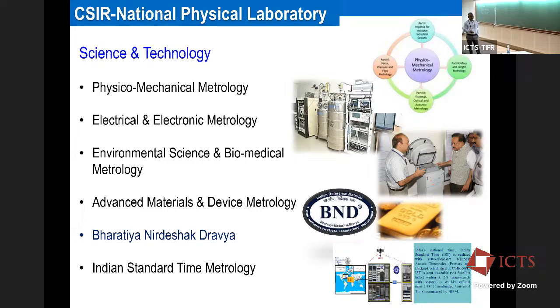And this is a precious metal reference material launched in 2016 as a Bharatiya Nirdeshak Dravya. Number is BND 4201. And then Indian Standard Time, we have an uncertainty of around plus minus 2.8 nanoseconds with Coordinated Universal Time, which is maintained through the BIPM, as we are the MRA signatory of BIPM. We also disseminate our time to IRNSS, which is the Indian Regional Navigation Satellite System. So 4 of the satellites are connected to this, and more are going to be connected. So this is the overall kind of activity which we have at CSIR-NPL.